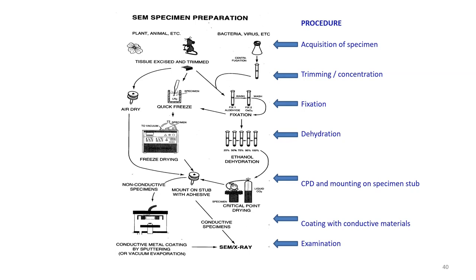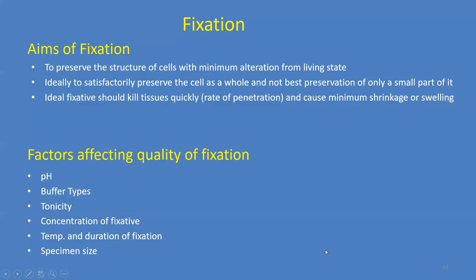You're interested in the surface features, and if it is shrunken, then it won't give you the information you're looking for. So there is a special procedure called CPD, or the critical point drying method. And after this, you have to make the specimen conductive. For that, you have to have a metal coating, typically with gold palladium. It's an instrument called the sputter coater, and then you examine your specimen.